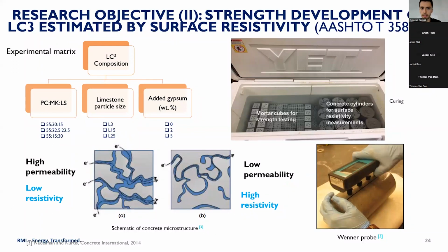The second study I want to mention today is the correlation between surface resistivity and strength development of LC3, an investigation I did during my research. In this study, I varied LC3 composition with respect to Portland cement, calcined clay, and limestone contents at 3 different levels. I varied the limestone particle size at 3 different levels. I also varied the added gypsum, which changes the sulfate balance of LC3, also a very important property. I cast 4x8 concrete cylinders for surface resistivity measurements, and using the same proportions, I made mortar cubes according to the ASTM standard for compressive strength testing.